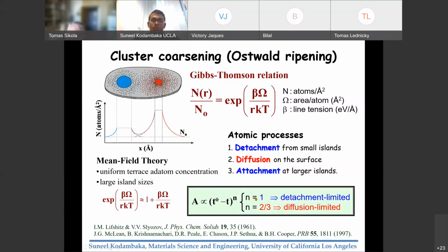If the scaling exponent turns out to be 1, meaning the area of the island scaling linearly with time, that would happen if the attachment or detachment of atoms at the step edges of the cluster is the rate limiting process. If that is the slowest process, then you would observe the area of the island to change linearly with time. And if the scaling exponent is 2/3, it implies that surface diffusion is the rate limiting step. Okay? So this is the classical mean field theory.